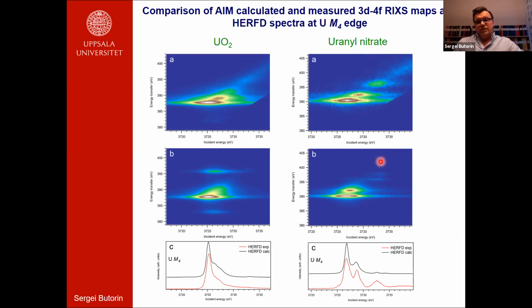For uranyl nitrate, the charge transfer effects and the hybridization become vital, so one has to take that into account. And the Anderson impurity model sort of reproduced these satellites, but of course they lack intensity, so more sophisticated calculations are needed. But the comparison of the RIXS maps is not so bad. I actually forgot to mention these tails, which correspond to the characteristic emission, which is of course not included in the calculations.